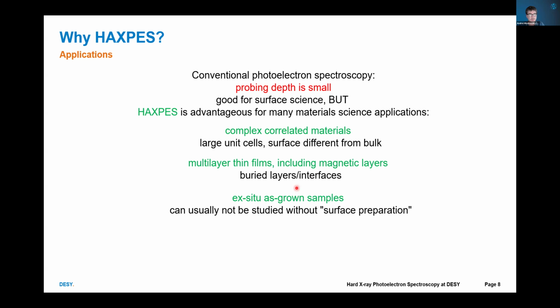Also, very good news for users: we don't really need surface preparation. We can use ex situ as-grown prepared samples without any sputtering or cleaving if needed. Or we can also use operando devices like ferroelectrics, which do need an upper electrode to switch the devices up and down. And our electrons from operando devices can penetrate through upper electrodes.